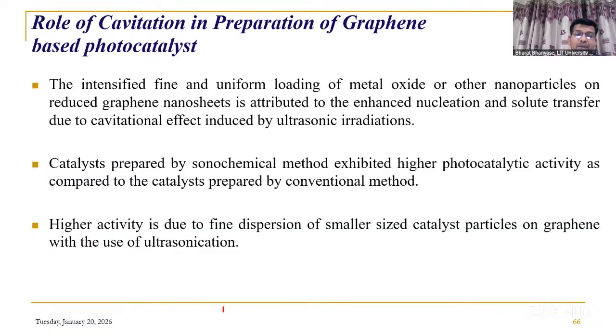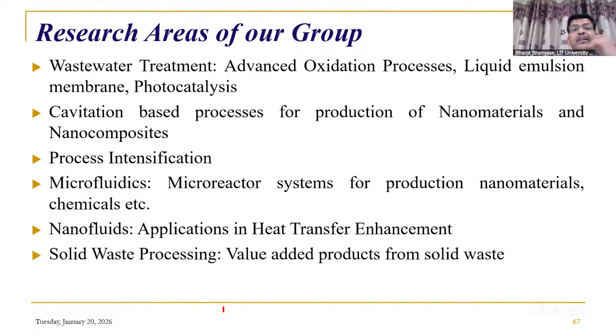So higher activity is because of fine dispersion, smaller size particles, so we will have more active sites, and degradation rate will be more in that case.